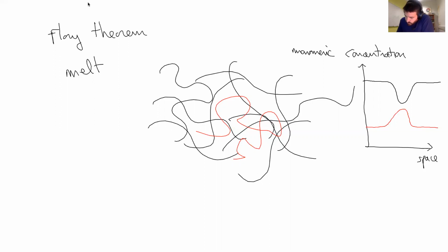So now, if you remember that the energy of interaction for one monomer, called U in the Flory picture, is typically given by kBT as a scale. Then there is the excluded volume parameter, which can be a function of temperature. And then it's proportional to the total concentration of monomers. So this is the energy of interaction that any monomer that you put in the system will feel, all right? So it's proportional to the concentration.